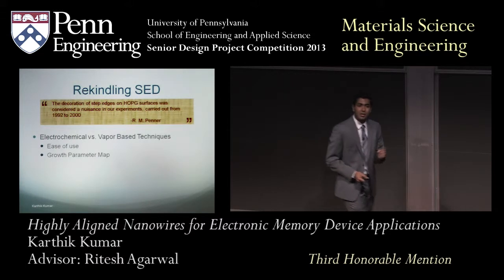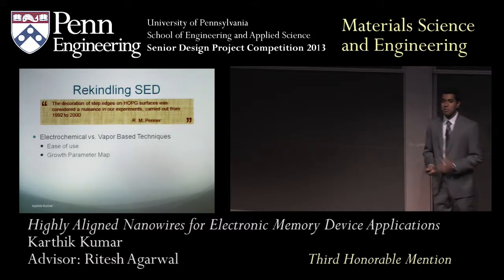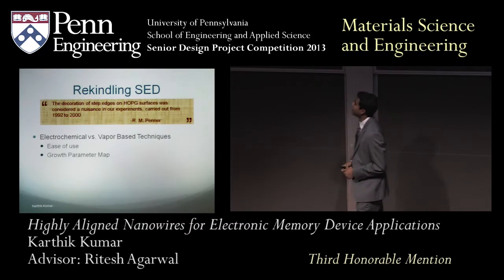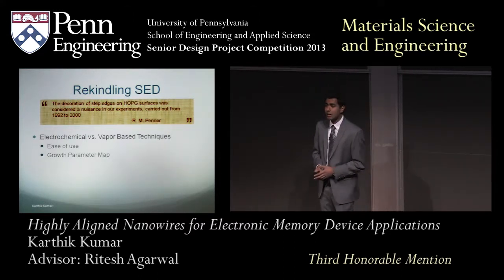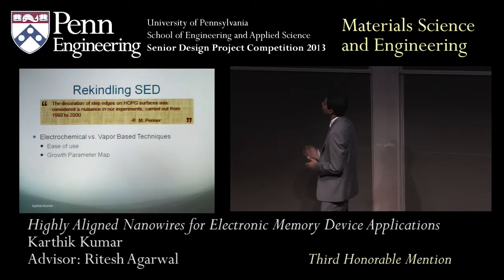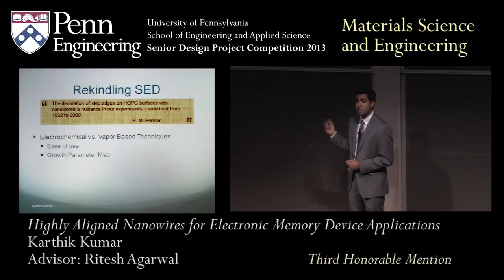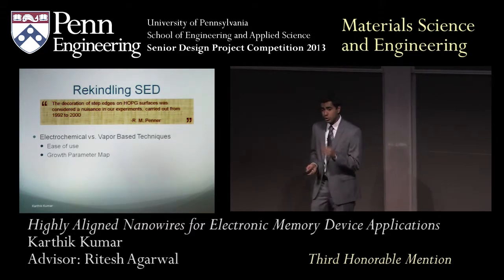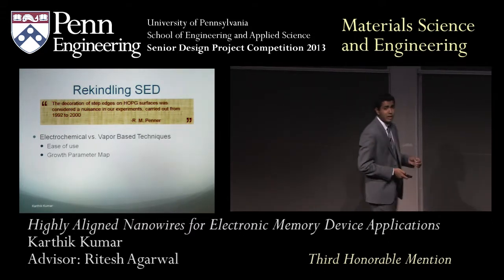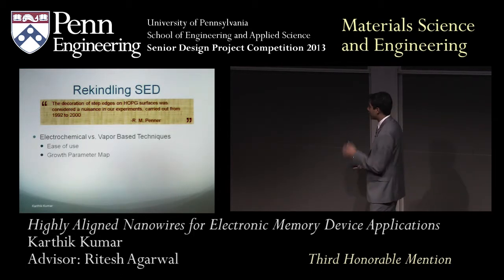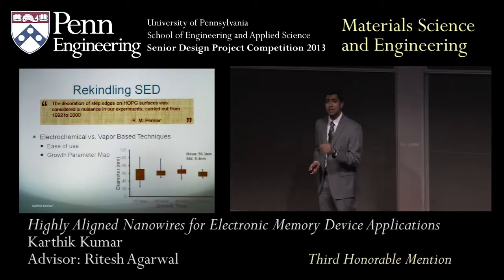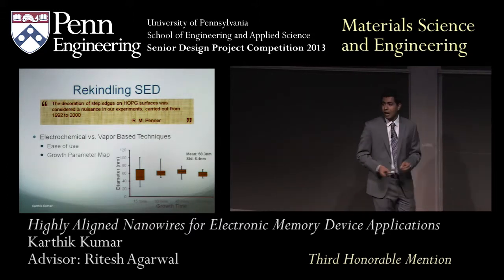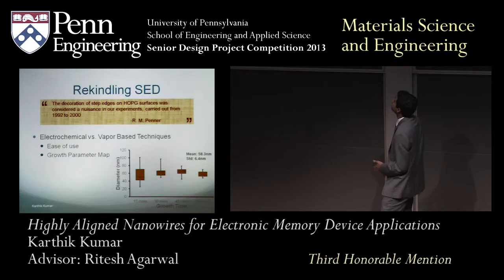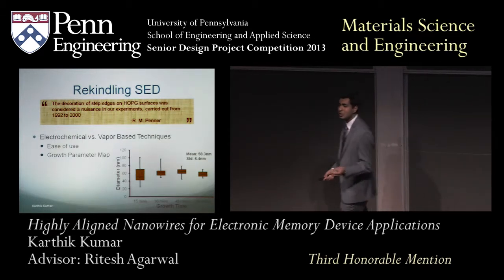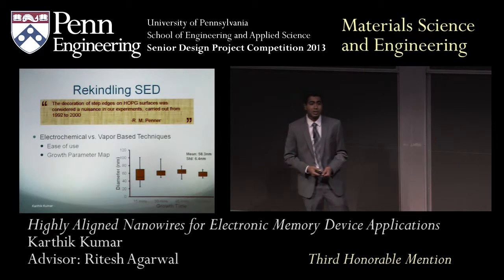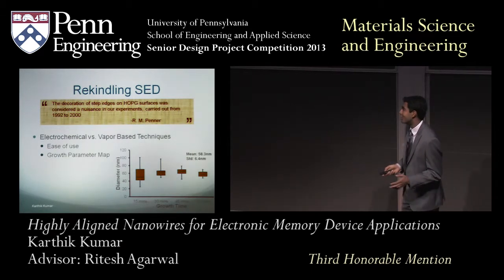For one, it's just easier to use. There's a reason why industry uses vapor-based techniques. They're easy to implement, and my method is very easily adaptable to a lot of different experimental setups. Next, we have a lot of growth parameters in vapor-based techniques. This allows us to tune the pressure, mass flow, temperature, etc., to influence the outcome of what wires we get. In fact, I've been able to very precisely control the diameters of my nanowires. As you can see here, the standard deviation after 60 minutes is about 6 nanometers, which is right in line with cutting-edge bottom-up technology today. So this process is really pushing the limits.